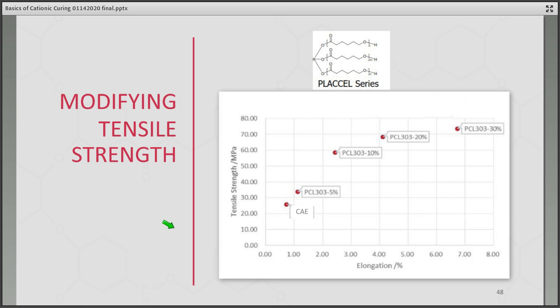Here's an example that I found in the literature on increasing the tensile strength by adding a polyol. This is from a Placcel series, a generic Placcel series. So we have these polyols here, and one particular was designated PCL303. Using our base, our workhorse cycloaliphatic epoxide, CAE, you get a tensile strength of very roughly around 27 megapascals. Adding 5% of PCL303, so adding 5% of this material, 10%, 20%, and so forth, we see we increased the tensile strength of your cured photopolymer from 27 to something in the low 70s. So a dramatic increase of tensile strength simply by formulating in this polyol.